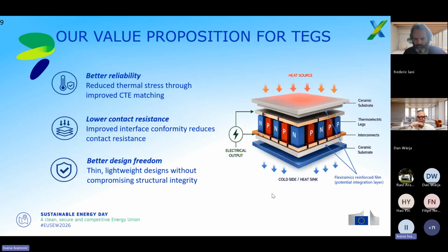The value proposition of flexible ceramics that FlexiRamics makes for thermoelectric generators would be in the CTE matching, which provides better reliability. When it is in a composite, as we make it for this application, it has a slightly conformable interface contact, which reduces the contact resistance. And it is very thin, 60 micron, 80 micron, so it's not compromising structural integrity, but gives better design freedom and lightweight options.